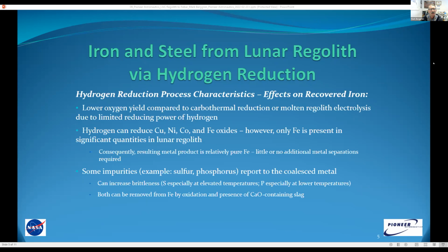We do get some impurities, and based on working with simulants, we see primarily things like sulfur and phosphorus that can report to the metal. Typically, we've seen less than 0.1 or 0.15%, but these can contribute to some potential deterioration of properties, but there are conventional and, with vacuum processing, even alternative ways to deal with that.